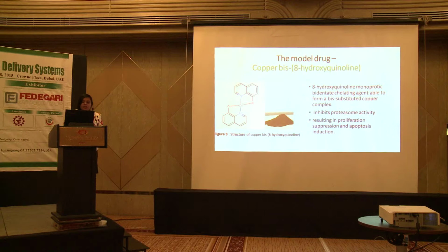For this study, the model drug I used is copper with 8-hydroxyquinoline. 8-hydroxyquinoline is a monoprotic bidentate chelating agent that is able to form a copper complex. So, this drug was encapsulated using calcium carbonate. The method I used is the co-precipitation method.